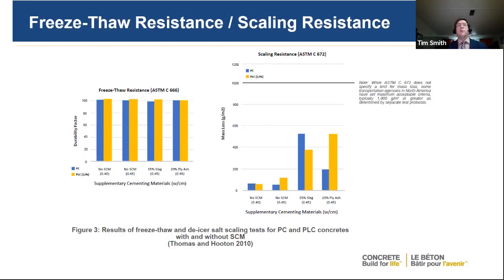If you look at freeze-thaw durability, the ASTM C666 test, you'll see that there's very little difference in the performance of the two cements. And if you look at the scaling resistance, there's a line here that's drawn. It's 1,000 because the ASTM C672 does not specify what is considered good scaling resistance, but some jurisdictions do in North America. And the value that they use is 1,000 grams per meter squared. And you'll see that in both cases, both cements are providing a much lower value than the 1,000. So there's no issue on the scaling side with either product.